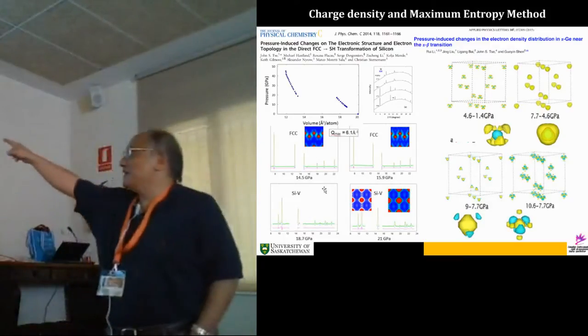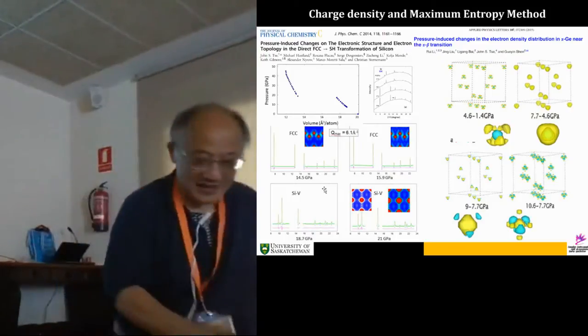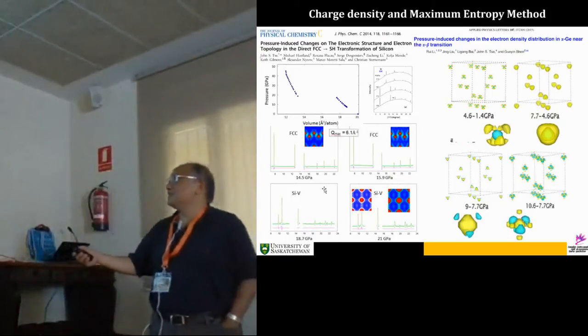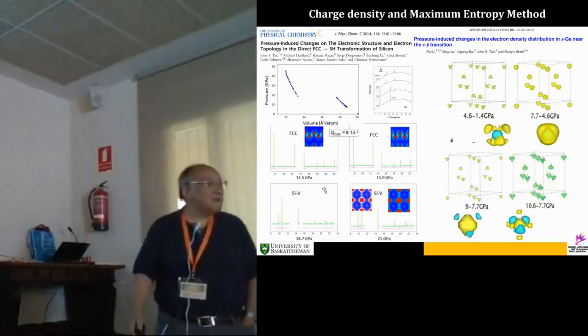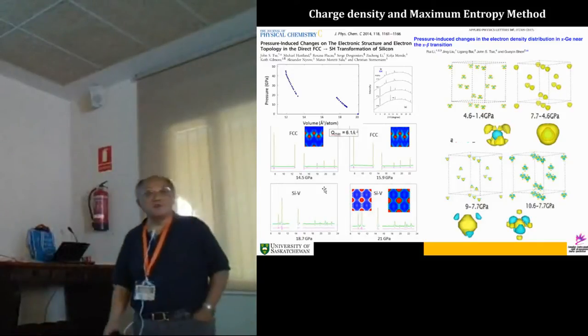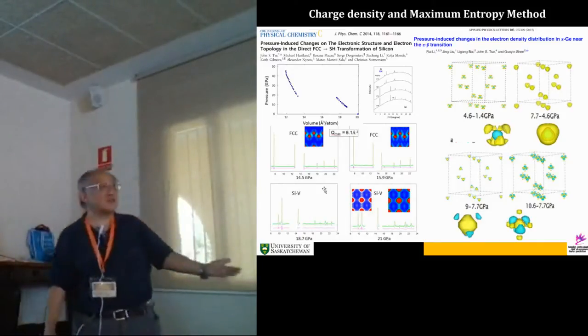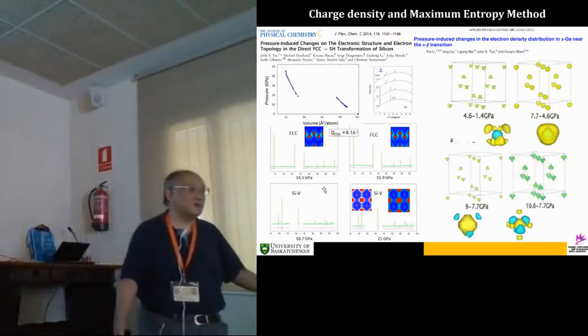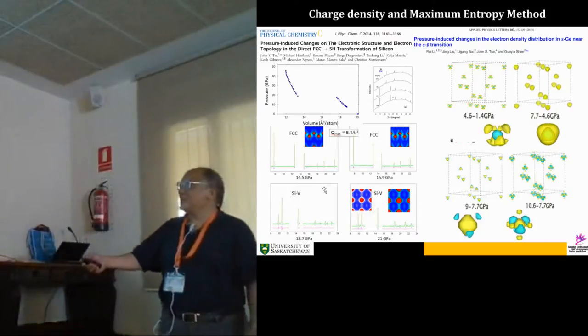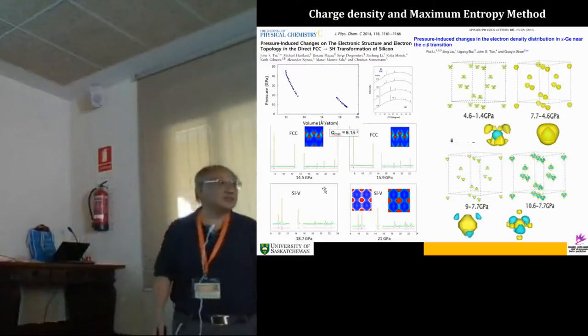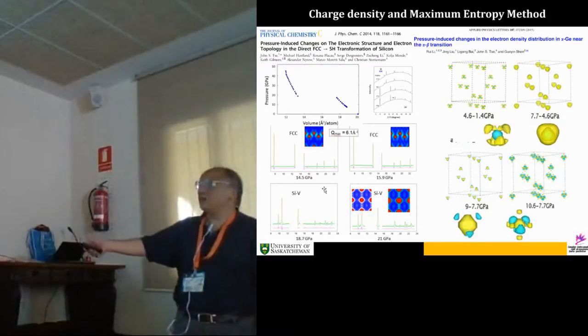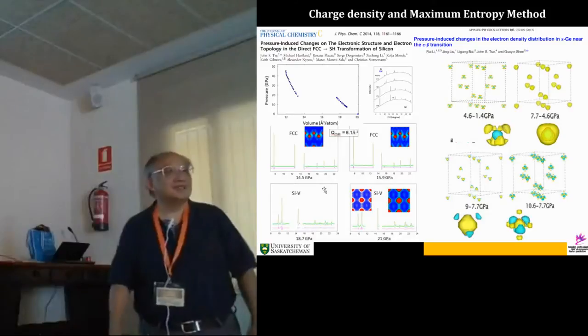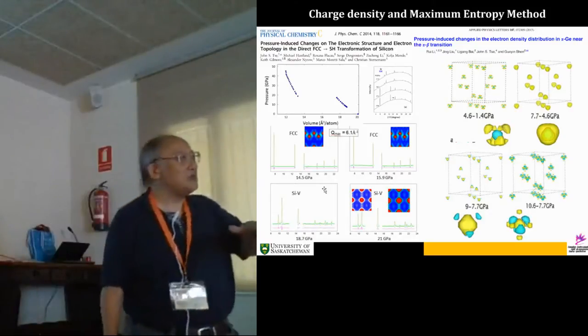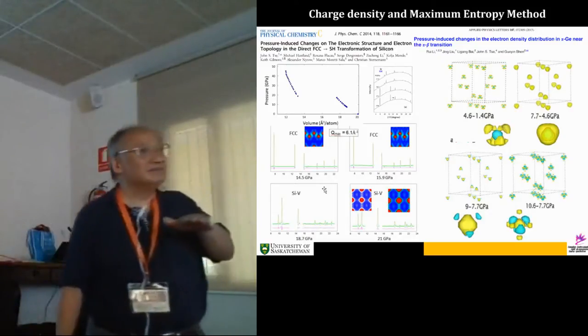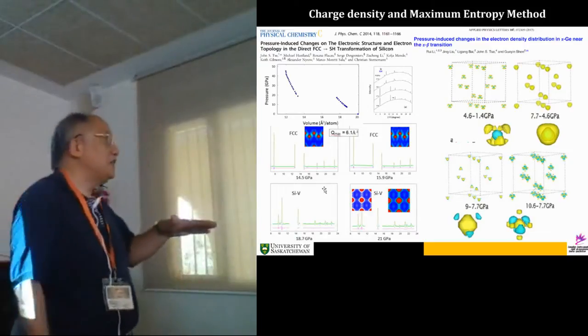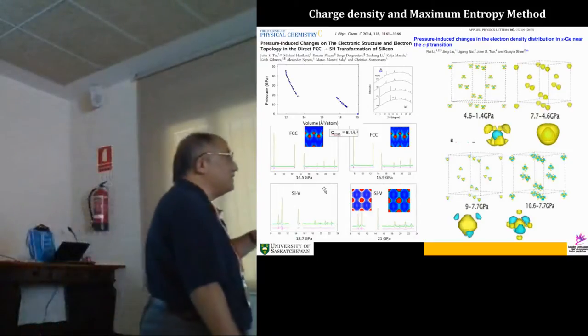So that's what I did with Han Fran. So we took the silicon in helium. And of course, all of you know the sequence of transformation of silicon. It's a prototypical high pressure study, right? We skip all the phases, we go to the hexagonal phase. We go here with a 25% volume decrease. Only 2 phase transitions in a hydrostatic medium at low temperature. All right? So all this total energy calculation, yes, correct.